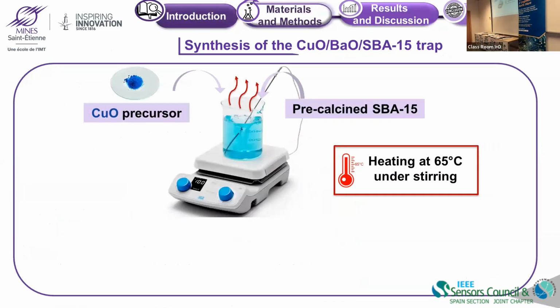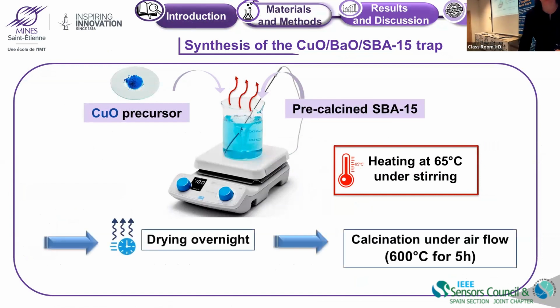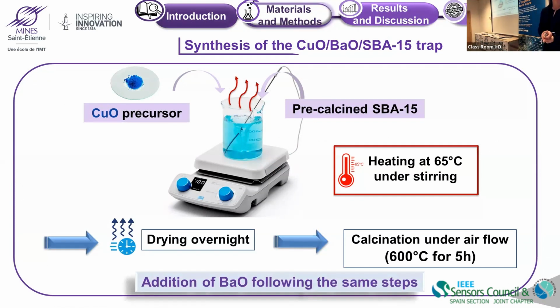For the preparation of the trap, we use the impregnation method. The copper oxide precursor is dissolved in water. The silica is added, and we stir the solution until total evaporation of the water. Then it's dried and sintered at 600 degrees for 5 hours. After that, we add the precursor of barium with the same steps.